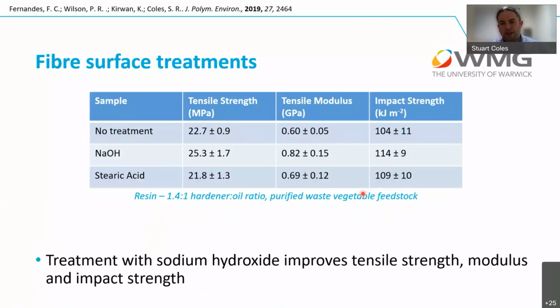So we looked at improving some of the fiber surface treatments to see if that would have an effect and improve the property of the composite. So instead of doing nothing to the fiber at all, particularly with the natural fibers, we looked at using sodium hydroxide or stearic acid as two ways of going about it. The idea with the stearic acid as a fiber treatment was to give a surface that would be similar in terms of its properties to the vegetable oil based network. So we've got that long fatty acid chain. Potentially that would give us a little bit more adherence between the two.